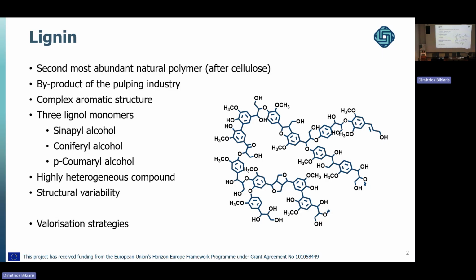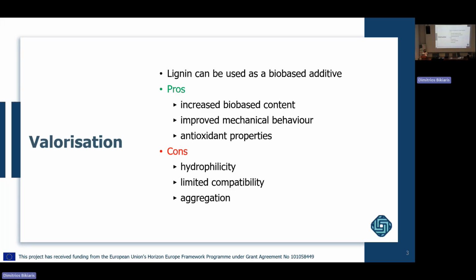And one of them is the use of lignin as a bio-based additive, which is a bit more straightforward compared to what Dr. Duval showed in the beginning of the workshop. The pros in using lignin as a bio-based additive is that we can, of course, increase the bio-based content of the final composite, and we can have, in some cases, improved mechanical behavior, and also some new properties that didn't exist in the polymer matrix, such as notably antioxidant properties. On the other side, lignin is a hydrophilic material. That means that we often have compatibility problems with the polymers, which tend to be more hydrophobic materials.